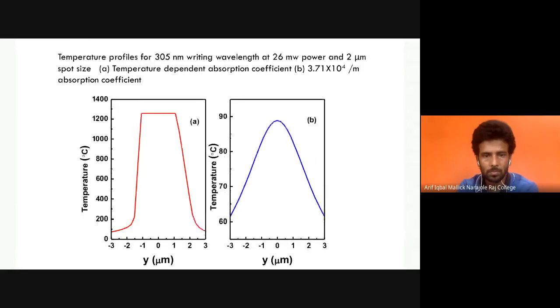From the introduction of the temperature dependent absorption coefficient, there is a huge change of temperature. If we consider alpha a constant, 3.71 times 10 to the power 4 per meter, then the temperature rise is 90 degrees, represented in figure B. But if we introduce our temperature dependent term, then there is a huge change of temperature, nearly equal to the melting point, 1257 degrees Celsius, which explains the formation of the waveguide and experimentally supports this model.